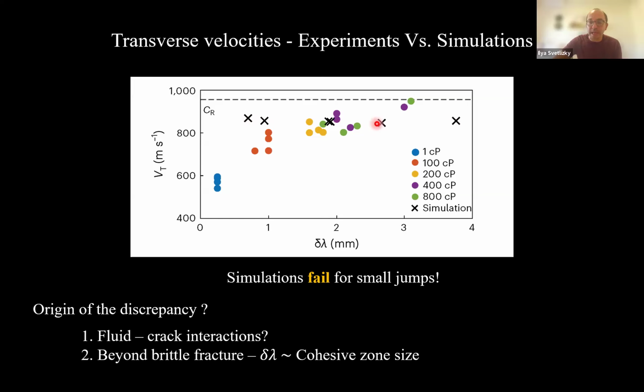In all these results, Gabriele made a lot of effort so that the brittle theory holds, meaning that the jump size is much larger than the cohesive zone size. By accident, we found out that it might not be the case, and when it's not the case, it slows down. The exact analysis we are still working on. I'm not sure if it will reproduce our results quantitatively, but at least qualitatively, we know that when the cohesive zone in the simulation is comparable to the jump size, the transverse velocity slows down. Gotcha. Thank you.